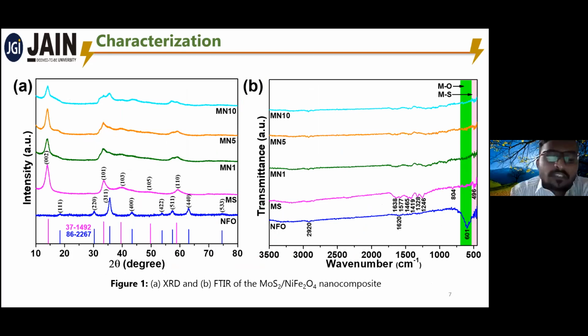Yes, sir. When it is a solo material, it is crystalline. But when it is merged with MoS2, it is a slightly amorphous material, and the concentration of the nickel ferrite is also less. Due to that, the crystallinity may be reduced, and a slightly amorphous nature is obtained with both these composites.